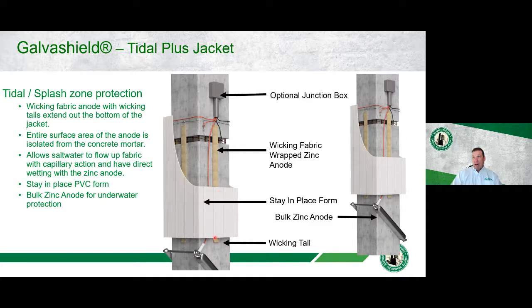So we don't have portions, you know, our bottom portions down here are not wet and these portions are dry. The entire portion of this anode is actually wetted from that capillary action that's taking place. Again, we have a bulk anode down here to take care of the submerged sections, and we have a stay-in-place form. One thing to note is the stay-in-place form can be a PVC stay-in-place form or a fiberglass form as well. So with this type of system, because we have constant wetting of the anode throughout the entire jacket system, we end up getting an increased performance with the system.